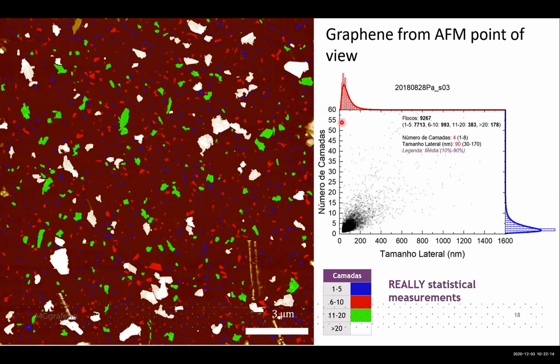When we do AFM, for example, we don't do AFM on 100, on 200 flakes. We do AFM on thousands of flakes, on 10,000 flakes. And this is really the picture of the material. This is what you really get, and this is what you can see. It's really statistical measurements that you can rely on. So the real material is this one. So its number of layers is around 4 in this case. The lateral size is centered around 90 nanometers, for example. Okay, so we do that for every batch.